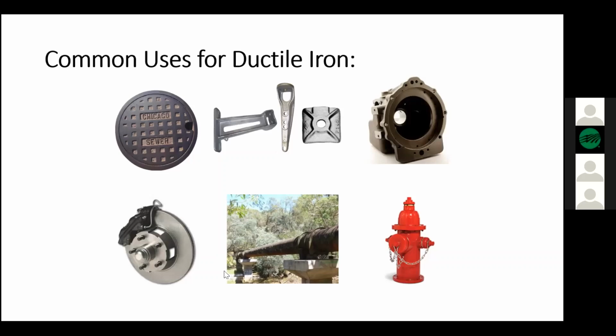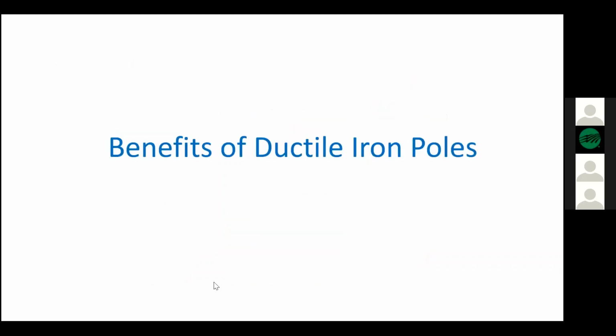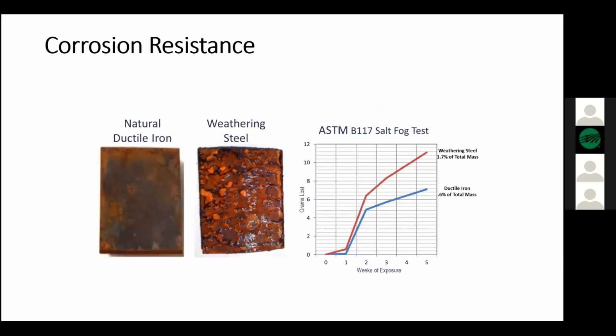It's brittle, where ductile iron is a little more flexible. So, benefits of ductile iron. Again, it's corrosion resistance. We did a salt fog test comparing ductile iron to Corten or weathering steel, and both pieces of material were exposed to the salt fog for a period of 5 weeks.